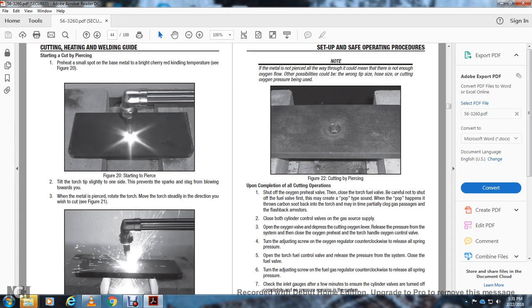Note: if the metal does not pierce all the way through, it could mean there is not enough oxygen flow. Other possible causes could be the wrong type or size of tip, the wrong hose size, or the wrong cutting oxygen pressure being used. Figure 22 shows the cutting by piercing.